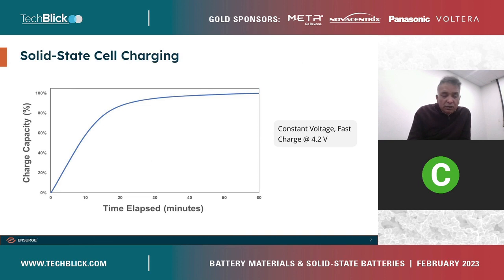So now let's get into quick points about the data. Here's an example of a cell where we showed how quickly it can charge. Unlike lithium-ion cells, where the charging has to be slower or more careful to prevent formation of dendrites, etc., we do standard constant voltage charging at 4.2 volts. This allows the battery to go to its full charge straight away, and we hit over 80% of the capacity in slightly over 20 minutes or so.